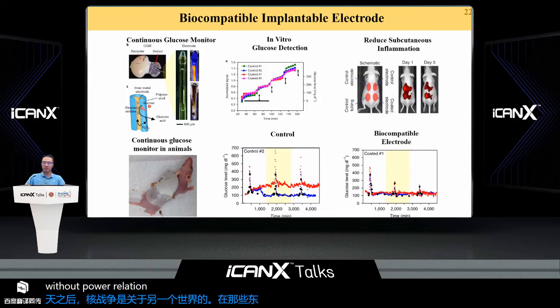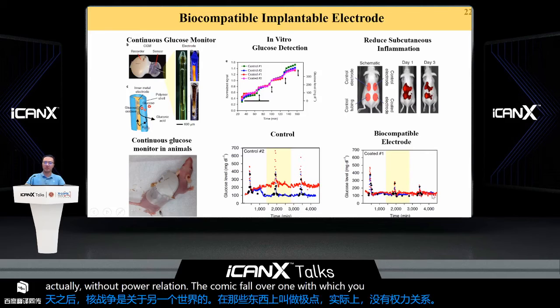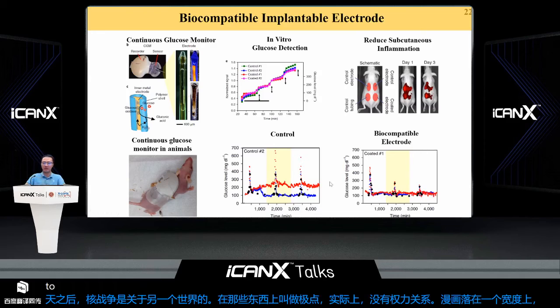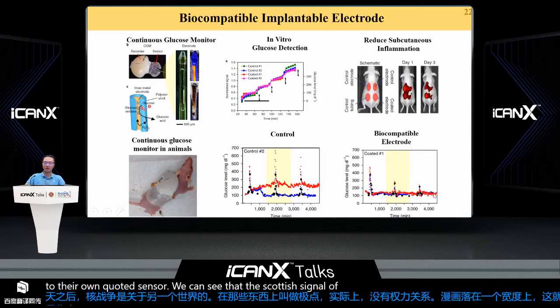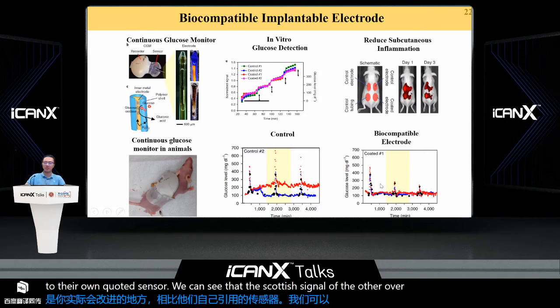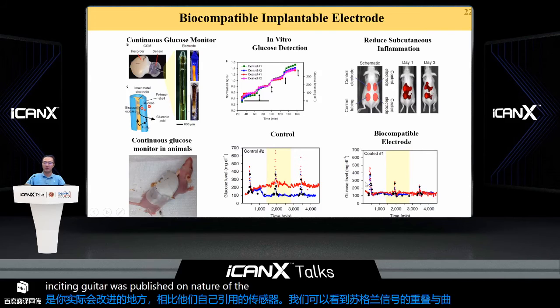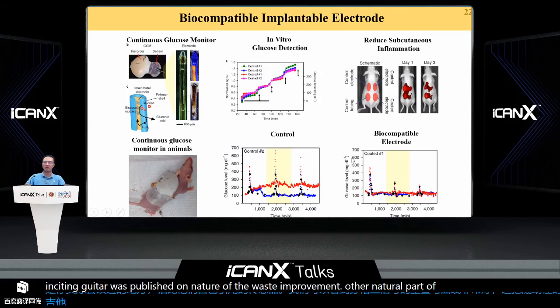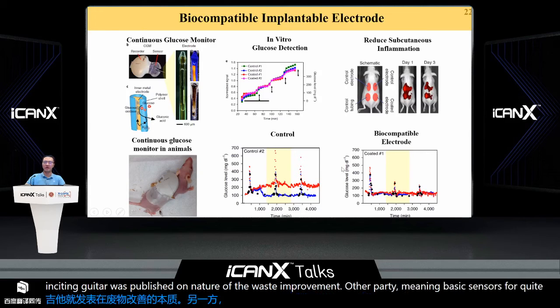The recording could remain stable for over 1 week, which is greatly improved compared to the non-coated sensor. We can see that the recorded signal of the red curve overlaps very well with the blue curve. This exciting result was published in Nature BME. With the improvement of the electro-biocompatibility, the minimally invasive sensor provides more useful applications in the future.